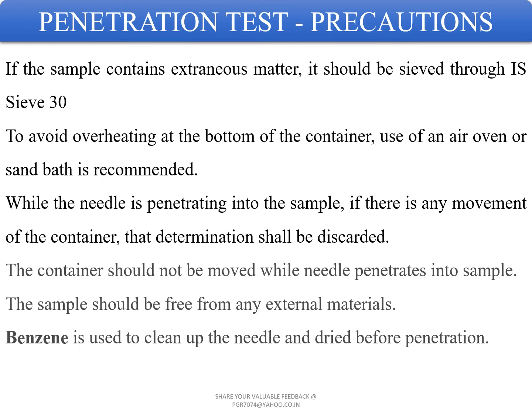To avoid overheating at the bottom of the container, use an air oven or a sand bath, because in this particular test you need to take extra precaution as far as the timing or the temperature of the test is concerned. If the temperature is more, the bitumen penetration value will change. If the temperature is less, the bitumen penetration value will again change. That means if the temperature is more, the penetration value will increase. If the temperature is less, the penetration value will decrease.